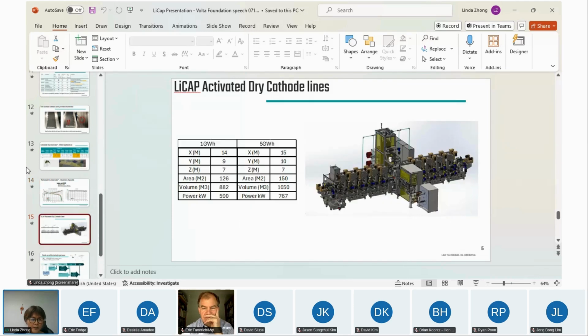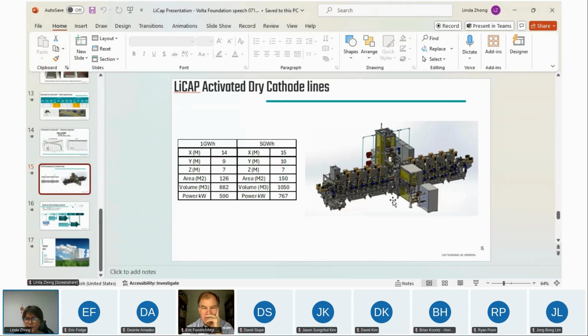Now we're talking about scale up. So this is a LiCap design of our activated dry cathode line. You can see we have 1 gigawatt-hour and 5 gigawatt-hour. So this is the total length of this machine. This is two films on the left side and the right side. You make two freestanding films together. In the middle, it's a laminator. So you see the machine total is about 15 meters instead of 100 meters for the wet electrode, right? And then you can see the space is very small. You can see the power usage is very small. It's a very precise cathode line.